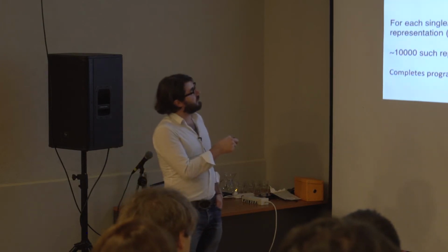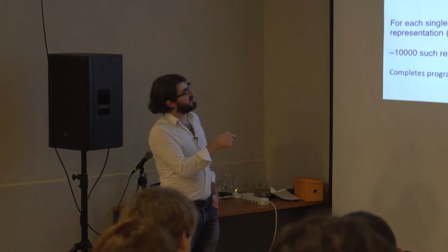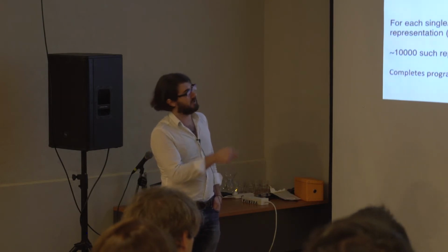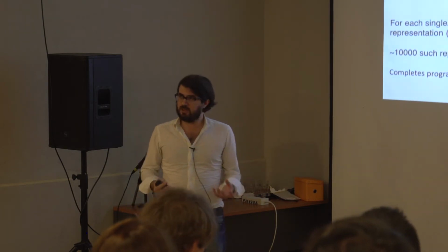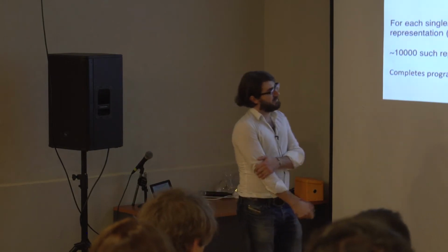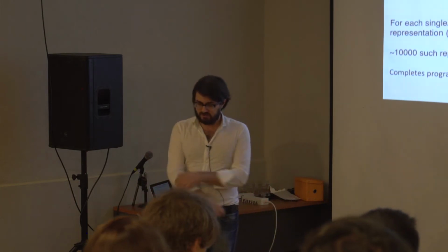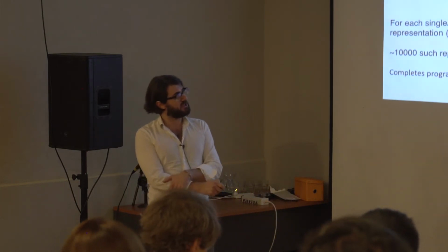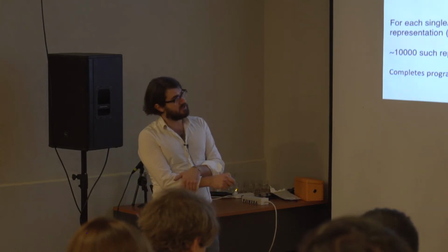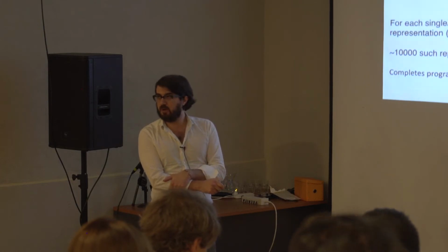And if I induce a representation into a subgroup of the space group and then induce it into the full group, that's just the same thing as inducing it into the full group. Basically, what these two things teach you is that the only things I need to look at to make a full characterization of the band representations are what are called maximal Wyckoff positions, which are Wyckoff positions with a site symmetry group that's a maximal subgroup of the space group.